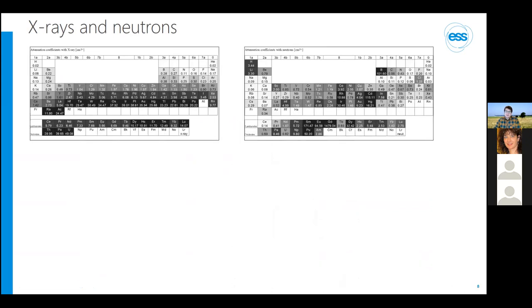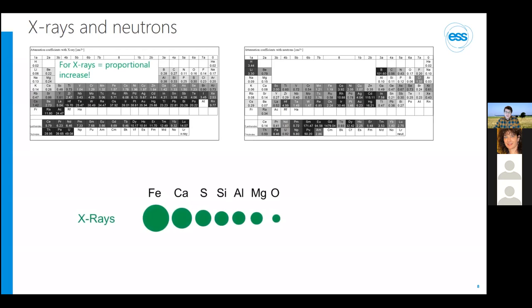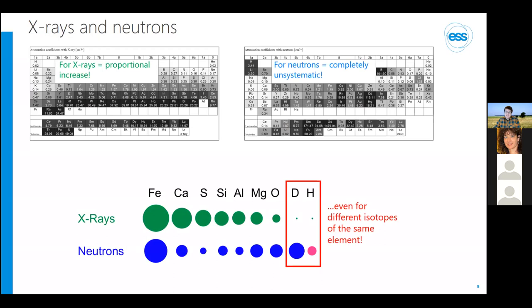A very useful thing to look at when you want to decide if neutrons might be useful for you is this type of periodic table that compares attenuation for neutrons versus X-rays. And these tables, or the information from these tables, Christine can maybe upload on the website later as well. So for X-rays, we have a proportional dependency on the elemental number, while for neutrons, the interaction appears rather unsystematic. And the interactions are even different for different isotopes of the same element.